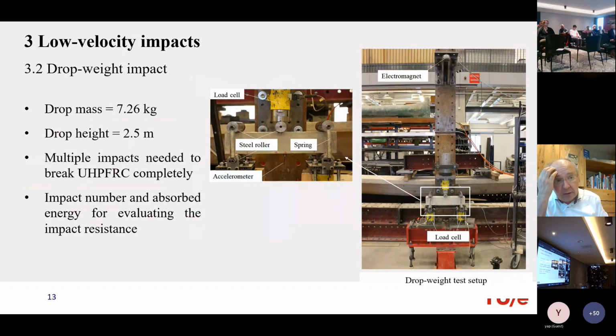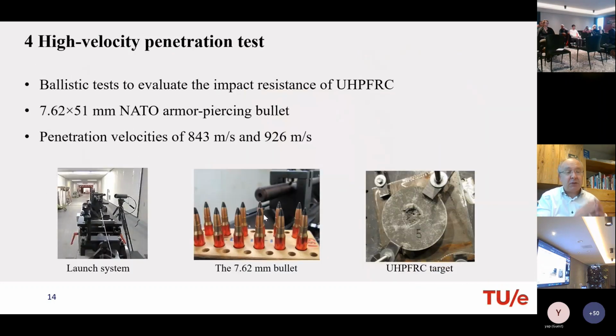There's also low velocity. We used drop weight impact. You can see it here. Here is the ball with an electromagnet. When you switch off the current, the ball will fall. It's 2.5 meters. We hit here, on top of this hammer, the beam and we measure the response of the UHPFRC beam.